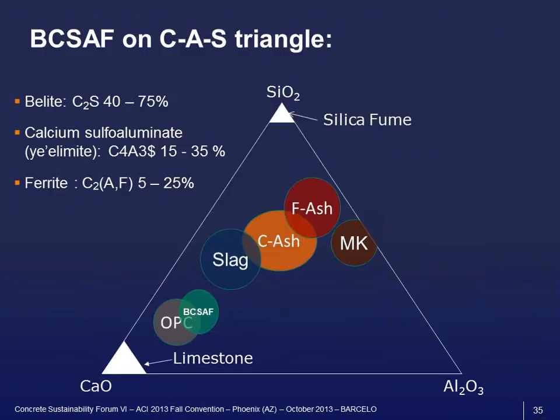Where it is in this CaO, SiO2, Al2O3 diagram, so it's about here. So you see it's not very far from ordinary Portland cement. Of course, there is a fourth dimension because there is the sulfate. So the belite is between 40 to 75%, so it's still the main phase. The calcium sulfoaluminate is 15 to 35%, and we still have 5 to 25% here.